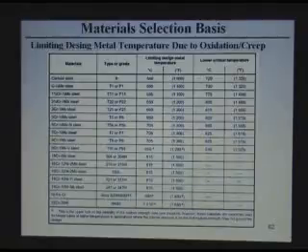So carbon steel, you should not use it above 1,000. Carbon half moly, you should not use it more than 1,100, and so on. Stainless steel can work up to 1,500. If you use HK40, you can use 1,850. And this is typically used in furnaces.